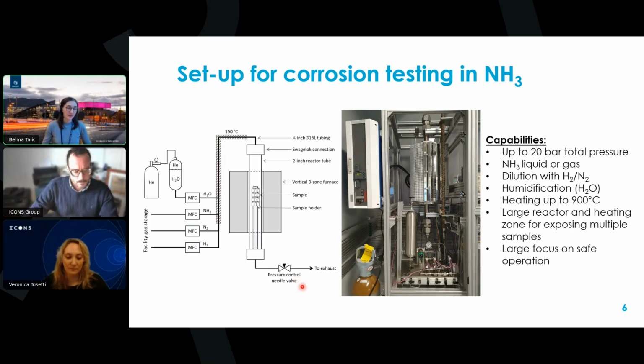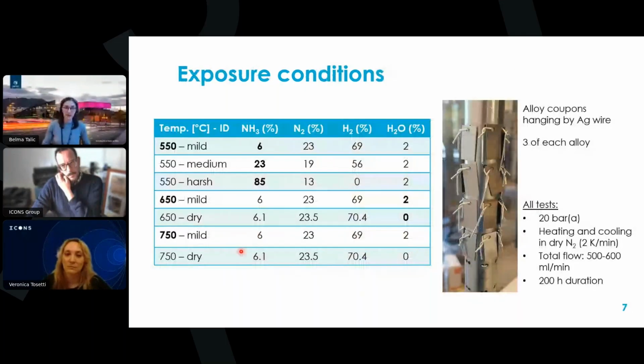So we do expect, since the reactor itself is made of alloy and we also have alloy samples on the way down here, that there is cracking of ammonia taking place. We also measure that by FTIR at the outlet, so there is probably a concentration gradient going from the top to the bottom. As I mentioned here, we have 3 samples of each type that we arrange on top of each other.